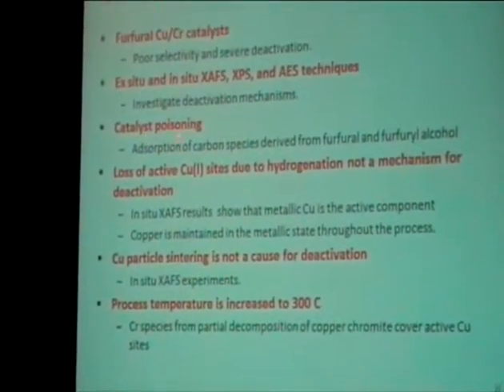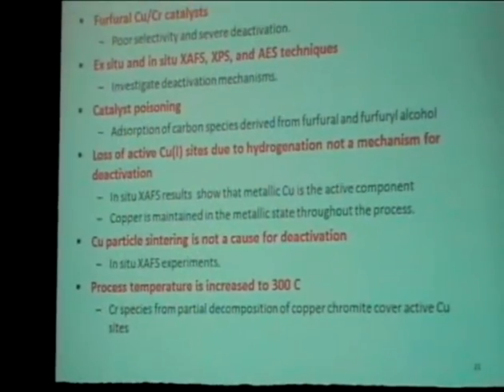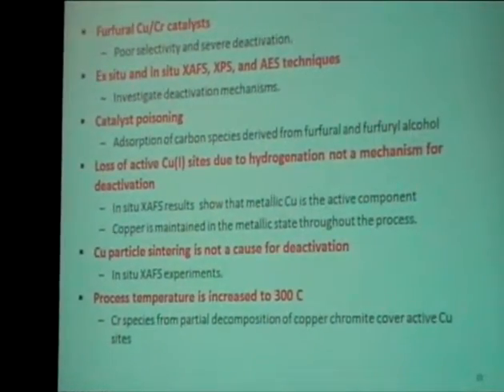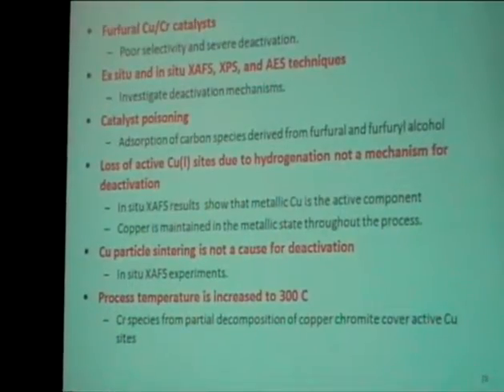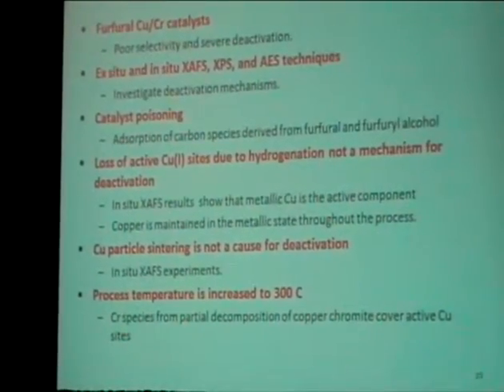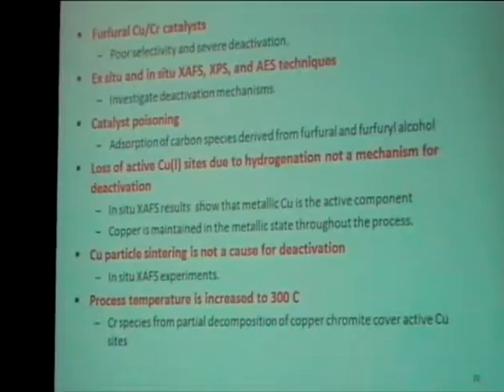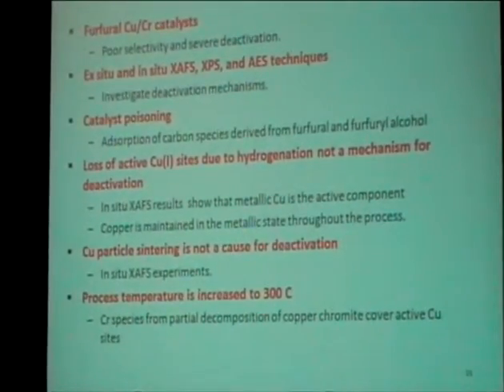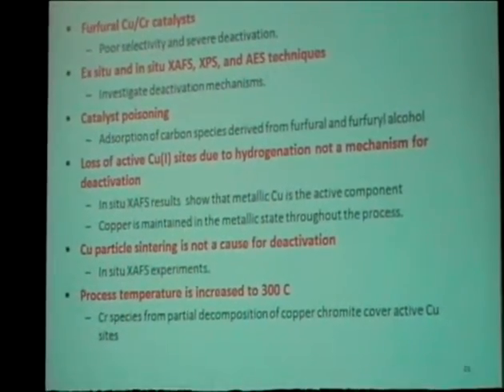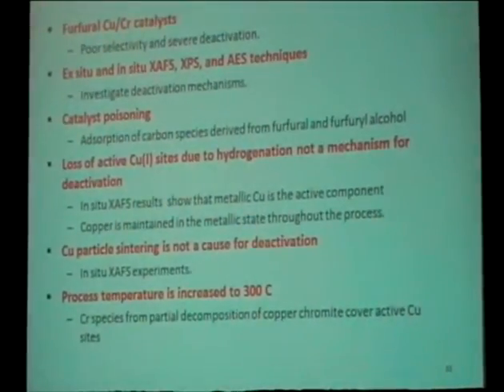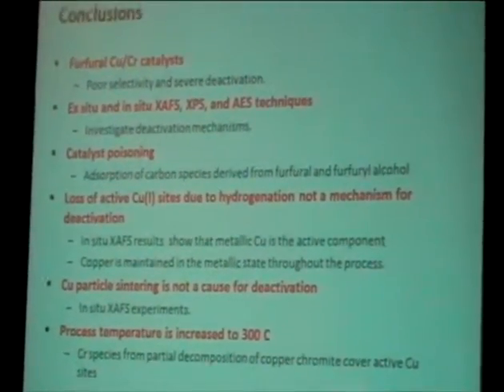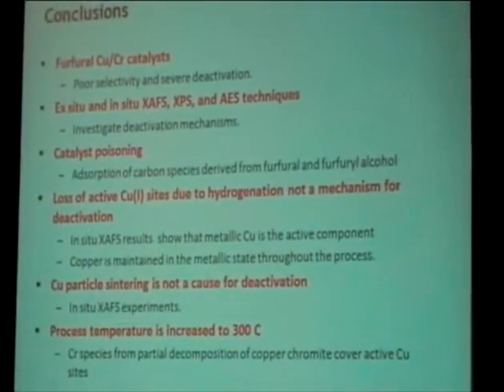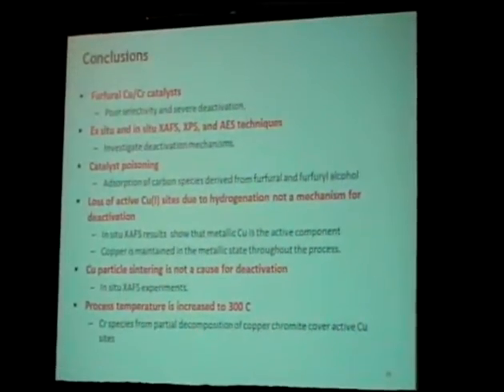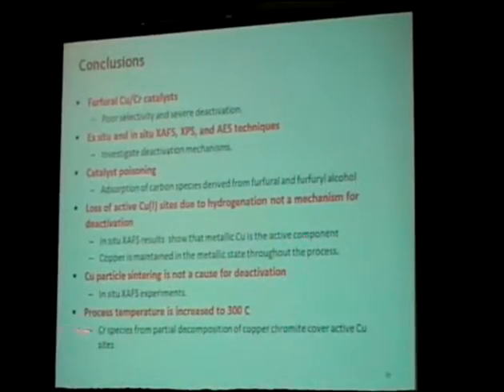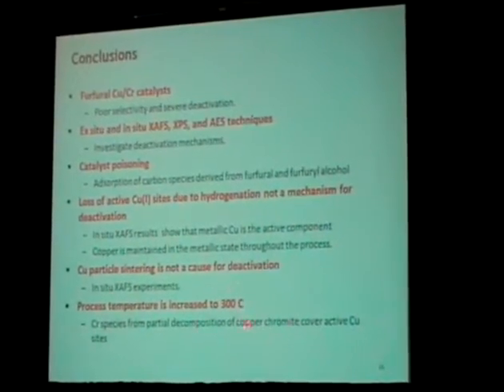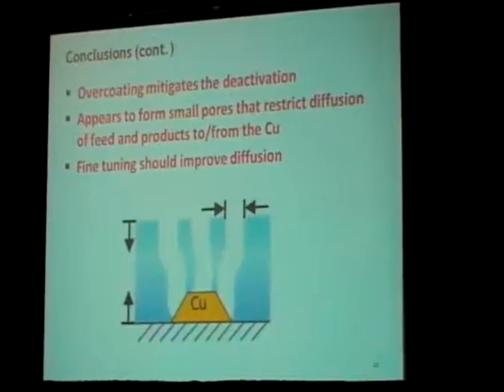First of all, the catalyst poisoning from the development of alcohol type materials that are absorbed onto the surface of the catalyst. And also we believe that the movement of the chromium over the top of the catalyst is also an important mechanism, especially as we deal with higher reduction temperatures for activating this catalyst at about 300 degrees.